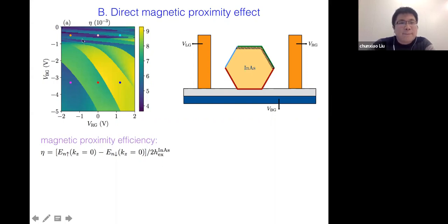So we see that this efficiency is a piecewise function of the gate voltages, and each piece corresponds to a particular subband mode closest to the Fermi surface. Although this efficiency is not a smooth or even monotonic function of the gate voltages, a general trend we can observe here is that when you tune the back gate to a more negative value or tune the right gate to a more positive value, the magnetic proximity efficiency will be larger in this direction.